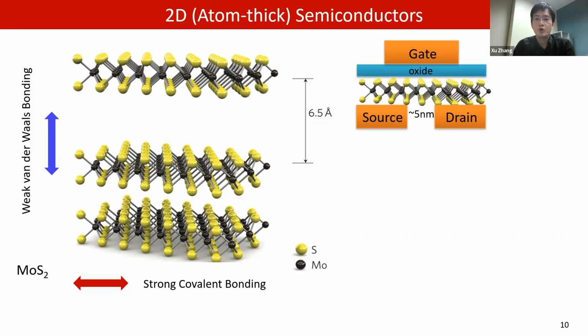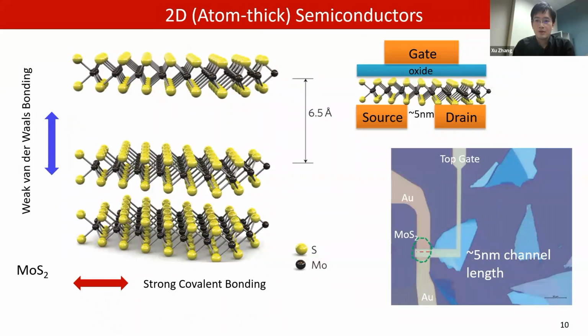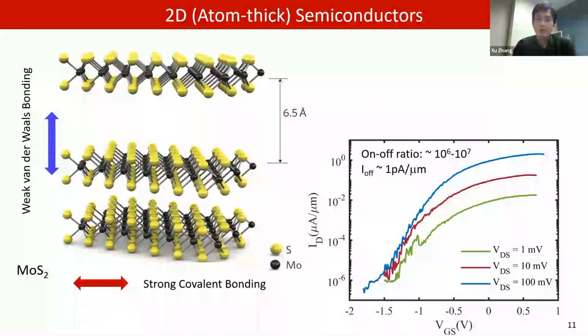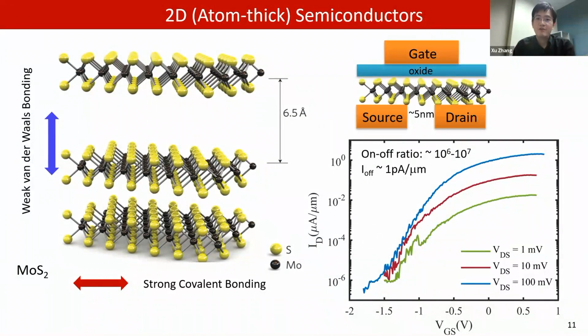Recently, we built an ultra-scaled transistor with bilayer MoS₂ as channel material, and we developed a new fabrication technique to scale the channel length down to about 5 nanometer. And here shows the performance of such a 5 nanometer channel length transistor. Thanks to the atom-thick semiconductor channel, we can get an on-off ratio around 10^6 and 10^7, even when the channel length is scaled down to about 5 nanometer.